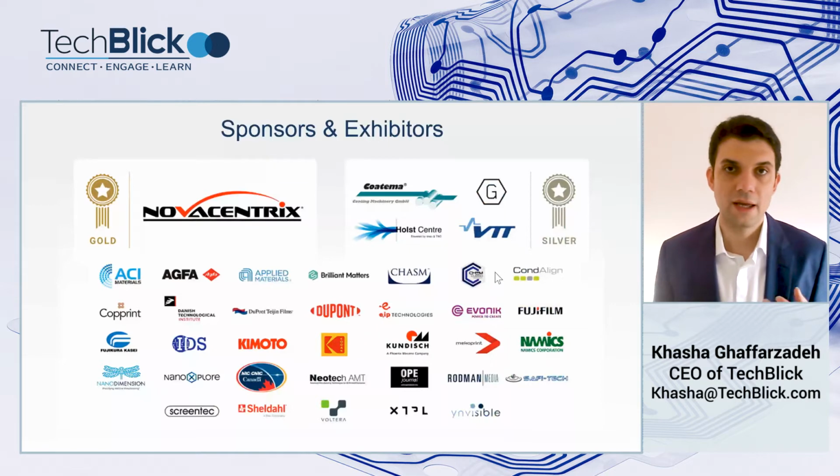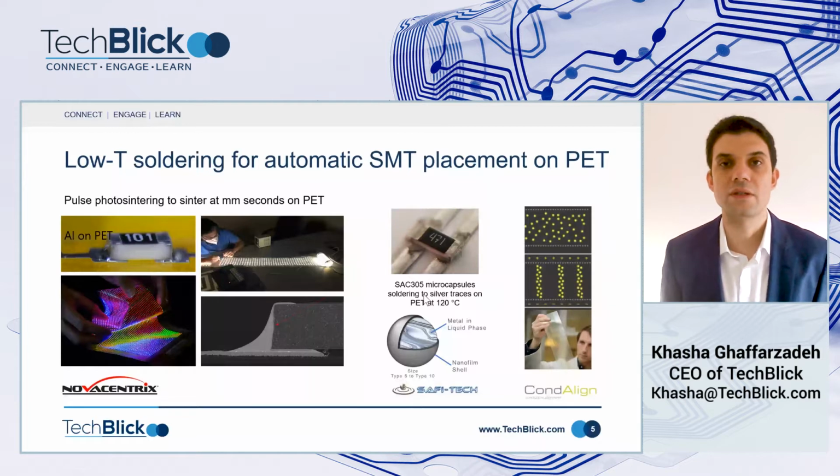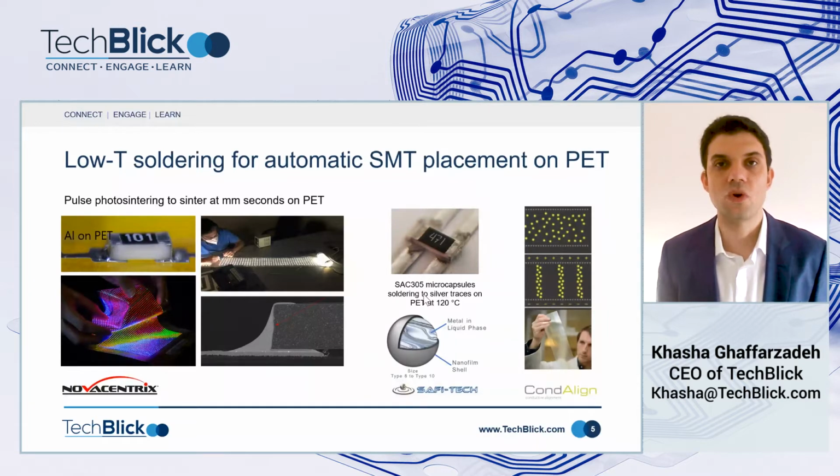And if you think about flexible PCBs, you will notice that many of the flexible PCBs are actually based on a PI substrate. And part of the reason for this is that PI can tolerate a relatively high temperature, allowing automated reflow process of soldering. This is part of the reason. Of course, one can still solder on PET, but usually this is done manually. And the reason is that when it is done manually, one can much better control the temperature profile of the soldering process, making sure that it does not exceed the constraints of PET.